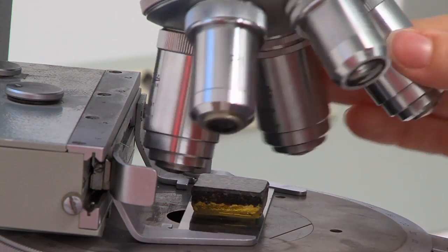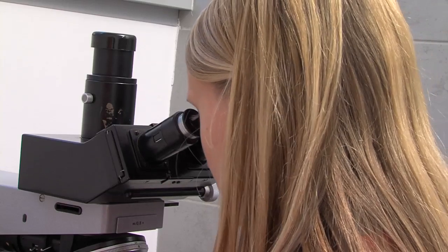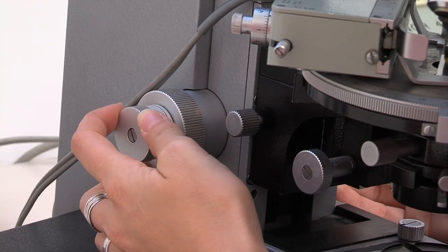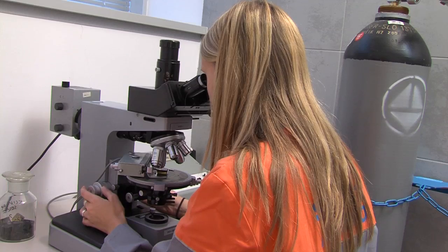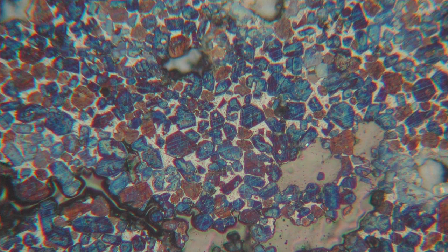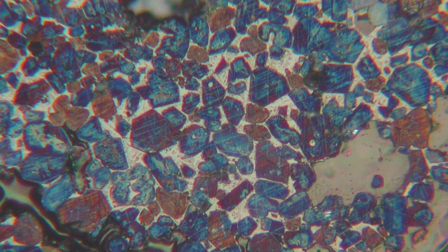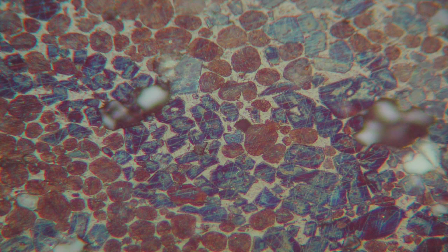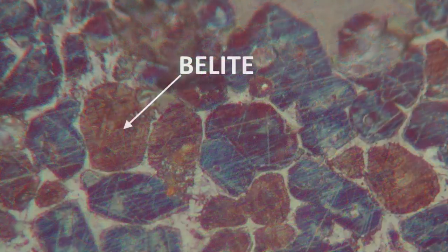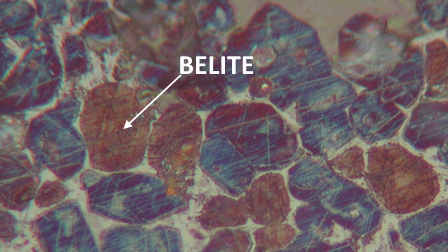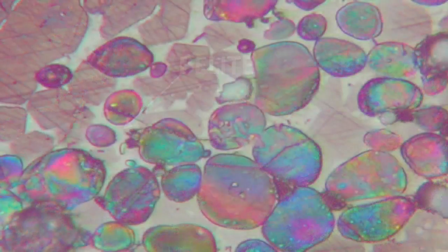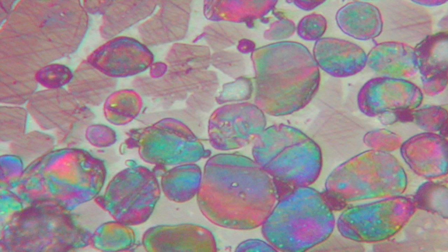Clinker minerals are clearly visible with observation under an optical microscope. The most important clinker mineral alite can be identified under the microscope by its blue color and sharp edges. It is very reactive and provides high initial and final strength in hardened cement binder. The second most important mineral, belite, can be identified by its brown coloration and oval rounded forms. The space between alite and belite is filled with aluminates and ferrites that are formed during the cooling of the melt.